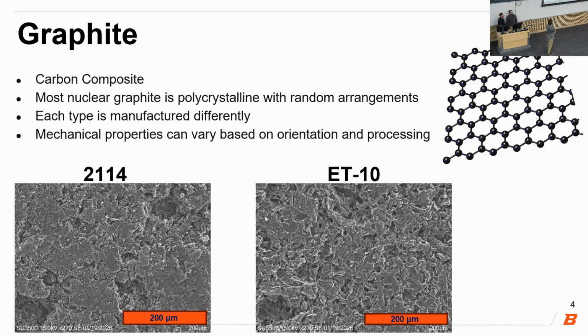A lot of the mechanical properties are dependent on what orientation you're looking at them, along with the background processing. Seen here are two different graphite grades we looked at under an SEM image. There's a pretty big difference in the microstructure we observed, and that's just based on processing.